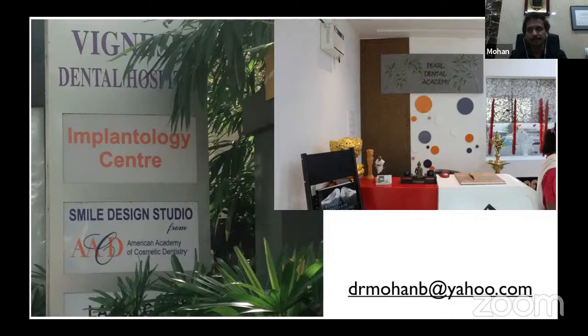Dr. Mohan, any role for IvoClean in any of these procedures? IvoClean is basically a product to get the surface treatment back. So I get a zirconia bridge from the laboratory and it's sandblasted already. The minute I try it in, the saliva contaminates it. Or somebody has asked for an Emax laminate to be etched in the laboratory and given to us, and I try it in the patient's mouth, it gets contaminated even under isolation. The surface treated gets contaminated with salivary proteins, and IvoClean would remove them. But here I'm doing the surface treatment on my own. So that means IvoClean has no role intraorally.